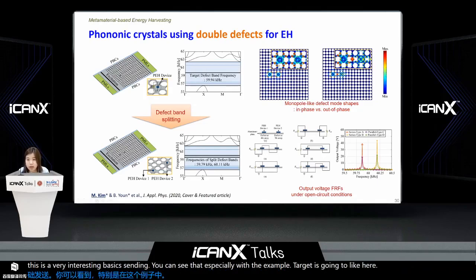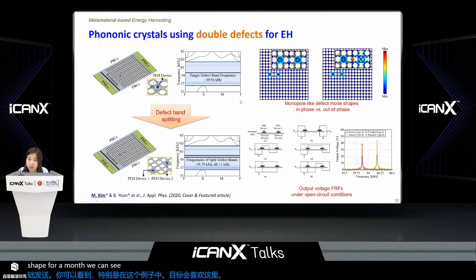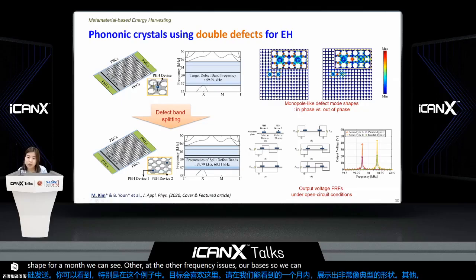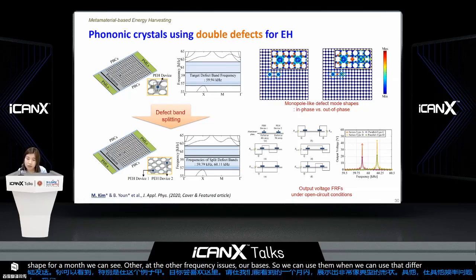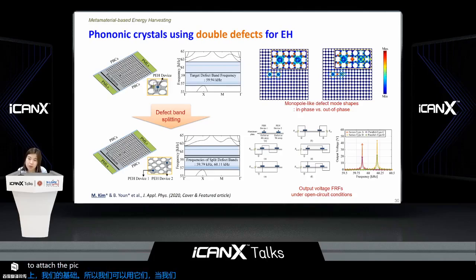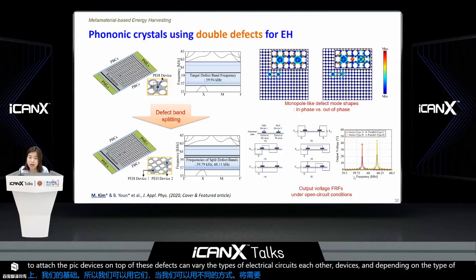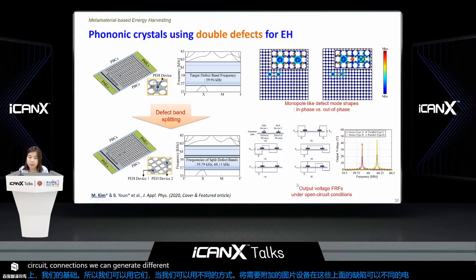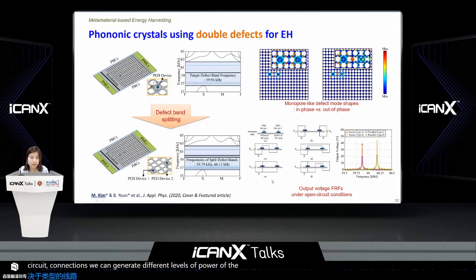They show a monopole-like defect mode shape, but at one frequency, about 59.7, the mechanical displacements appear in phase, while at the other frequency they show out of phase. So we can use them differently when we attach piezoelectric devices on top of these two defects. We can vary the types of electrical circuits connected to each piezoelectric device, and depending on the type of circuit connections, we can generate different levels of power out of these two defects using phononic crystals.